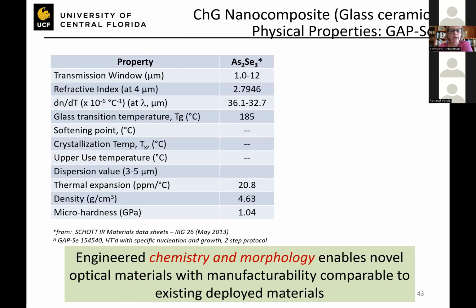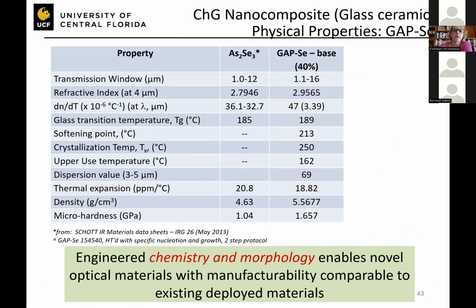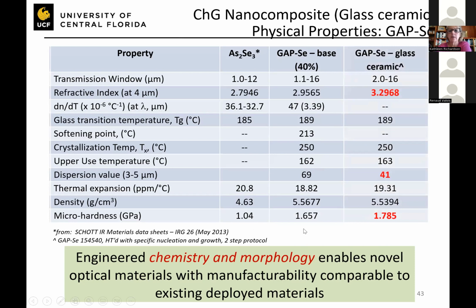So what are the changes of these properties then when I create this secondary phase containing glass ceramic? Well, I show the key properties, and I lifted this table from the SCHOTT data sheet. Here are the properties shown in their data sheet for arsenic triselenide. And here are the properties of one of our base, we call GAPSe, germanium arsenic lead selenide base glasses, where the lead selenide content is 40 mole%. Here is the base glass, so no crystals. Here are the properties of the base glass. And here's what happens when I use a controlled nucleation and growth protocol.